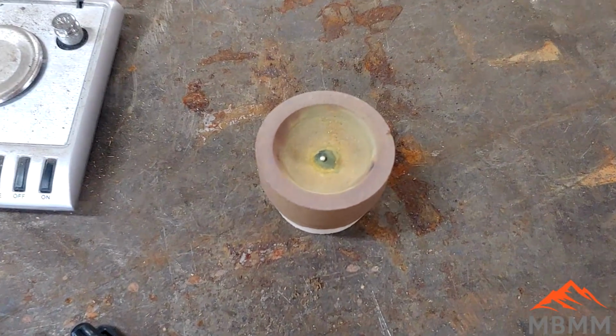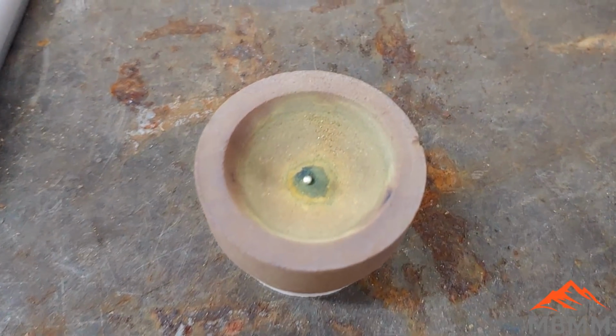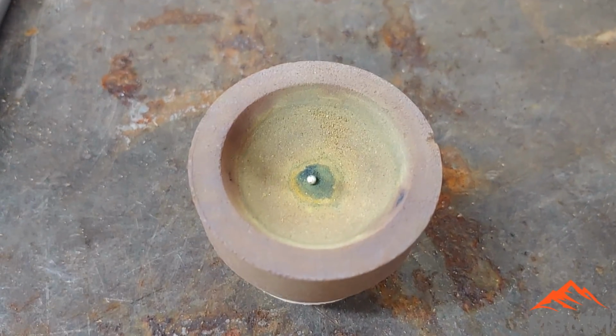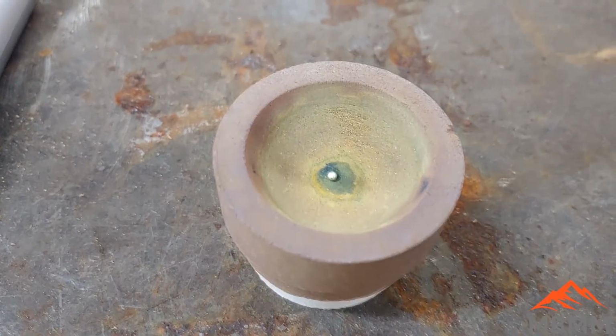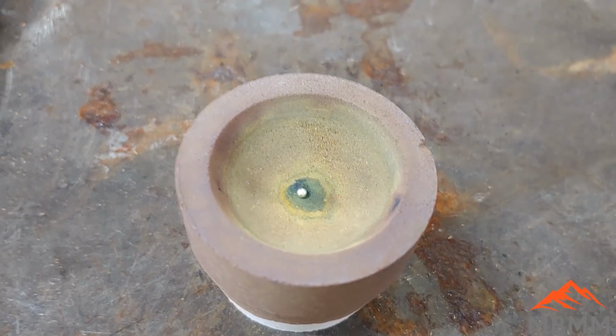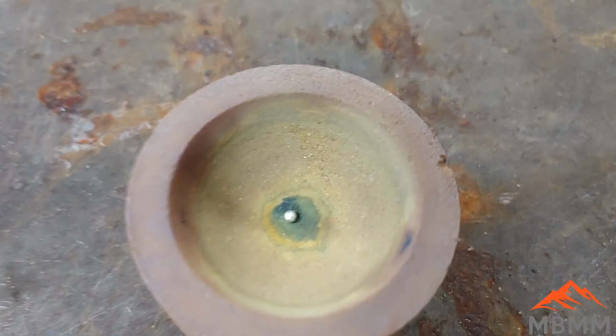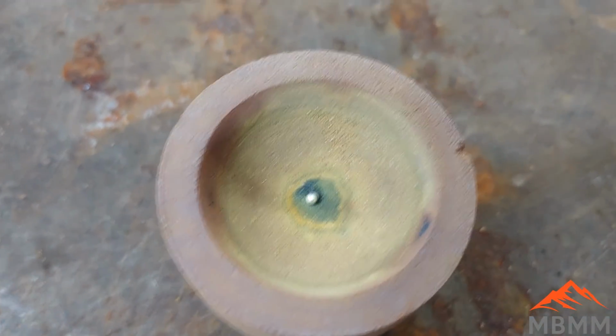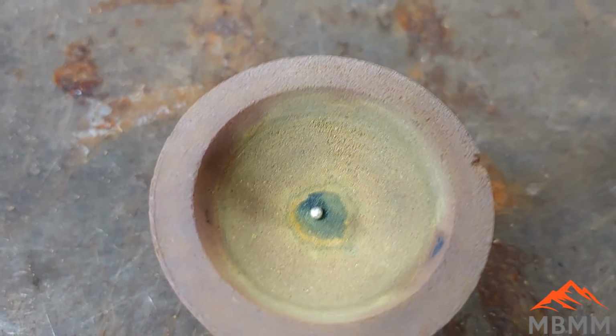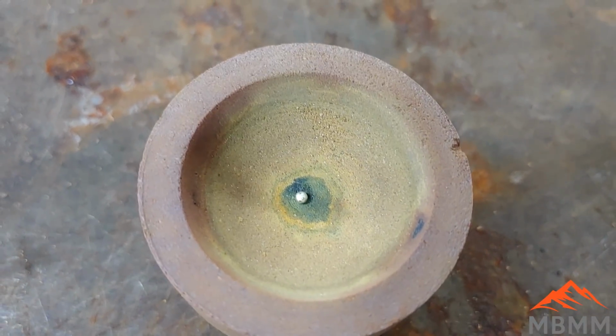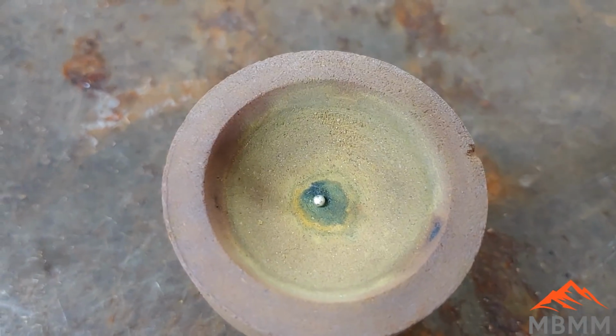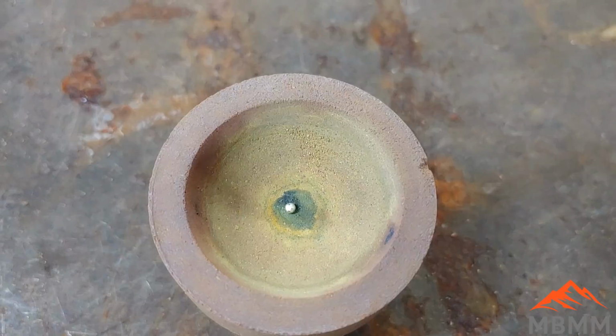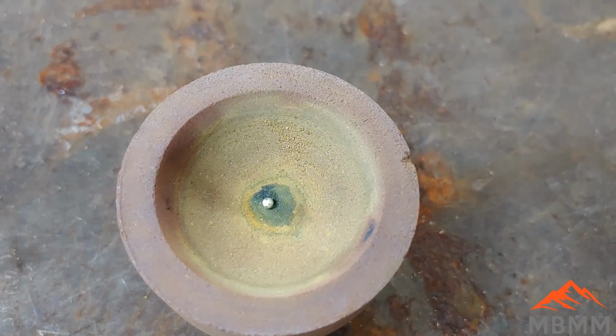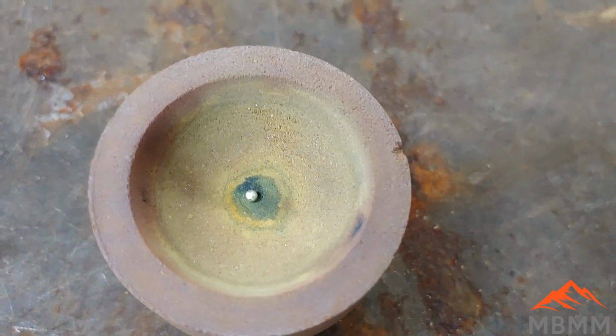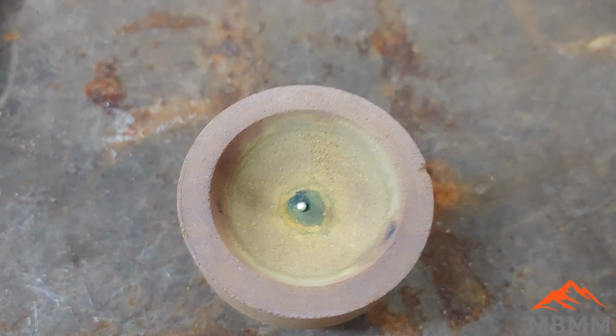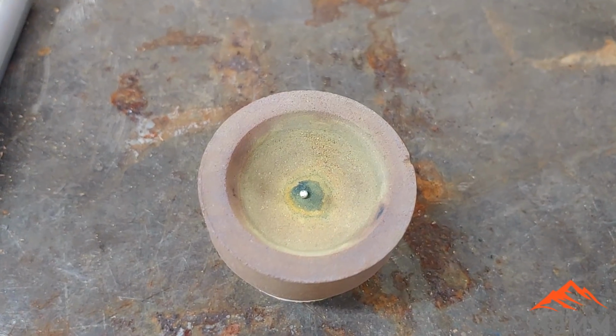One more thing I'll mention here real quick. Now that it's cooled down, you can see in the cup of that cupel, that real yellow, lemon yellow color is from the lead oxide. And then right there around the bead is that dark greenish black. That's either iron that was contamination in the bead or a little bit of copper that was contamination in the bead. But you can kind of tell from the oxides what the bead has in it. But that's not a bad little bead for just a 100-gram sample.